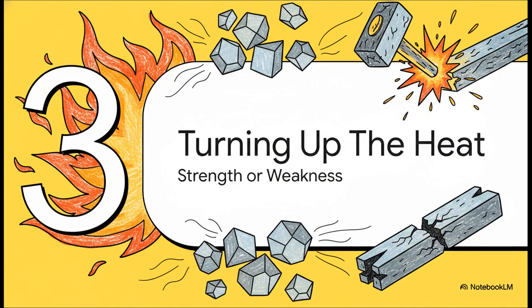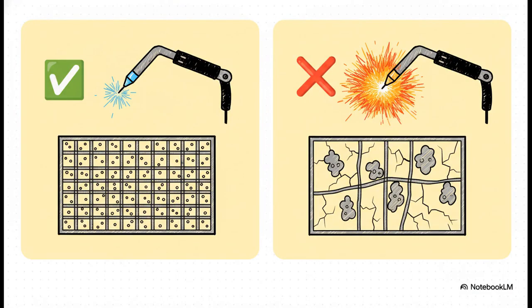Now, the first big lever that engineers can pull to get these precipitates just right is heat. The energy from the welding process itself is this double-edged sword that can either forge amazing strength or create some serious weakness. It is a serious balancing act. What you really want is a lower, more controlled heat. That helps those perfect fine precipitates to form, and it refines the whole internal structure. In fact, some research shows that when you optimize this with something like low-heat laser welding, you can get joint efficiencies up to 93%. That means the seam is nearly as strong as the original metal, which is a massive deal for safety-critical parts. But if you crank that heat up too high, you get these clunky, brittle compounds that actually make the welds softer and weaker.